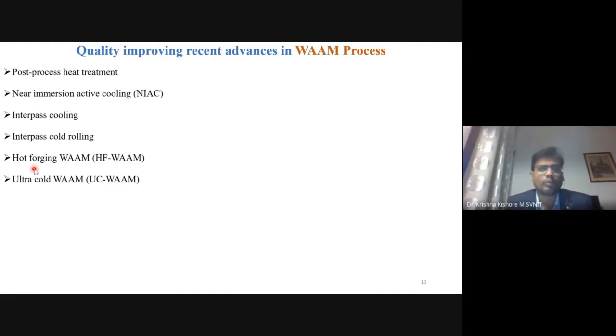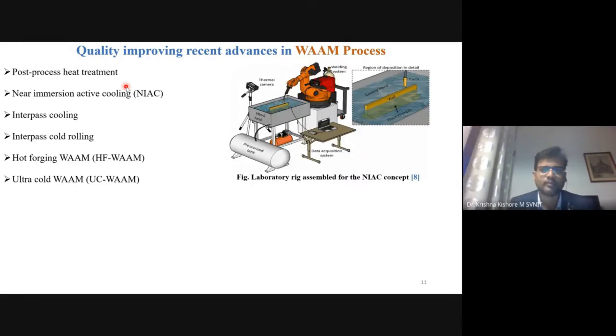That is one drawback, the anisotropic properties from the bottom to the top. The other disadvantage of this process is distortion. When we deposit continuously, even in our lab we have observed that if we deposit around 120 layers continuously, after cooling there is a bend, some distortion in the shape. If you are expecting a straight deposited sample, we can see a little curvature at the ends. This distortion is because of residual stresses. These residual stresses can also be controlled by post heat treatment, by maintaining some interpass cooling, or by continuously doing interpass rolling. Okay.